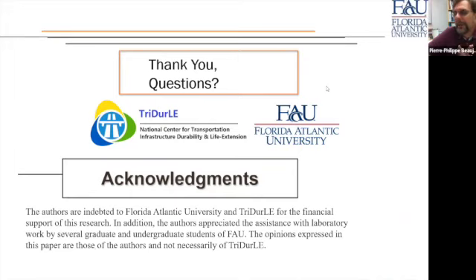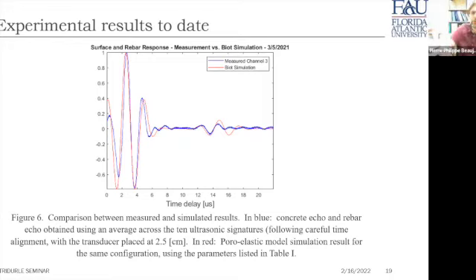What happens is that you see there is the blue signature measured and the red signature, which is modeled. To actually get a match of these combined echoes, you need to perform a match one frequency after the next of the response of the medium to the acoustic signal we transmit.